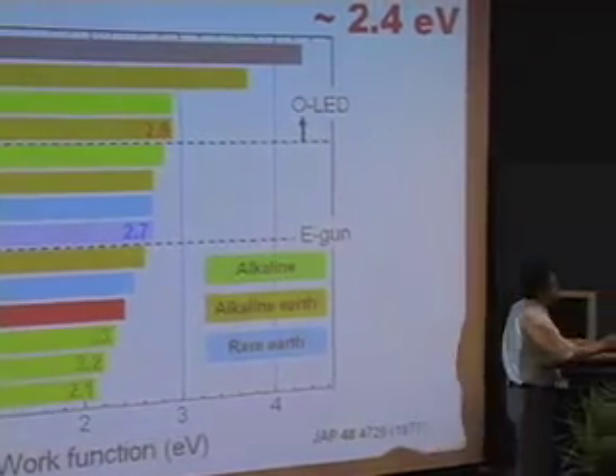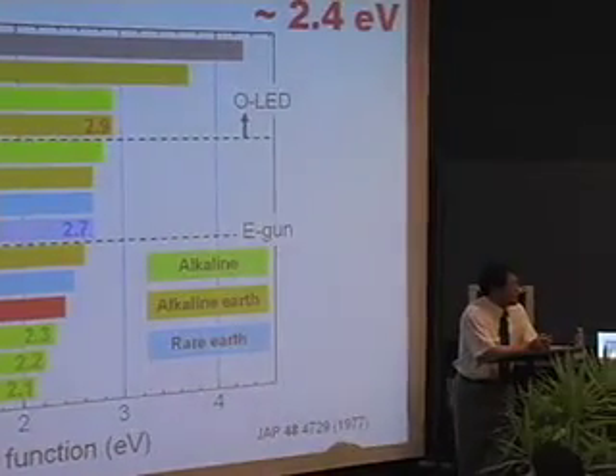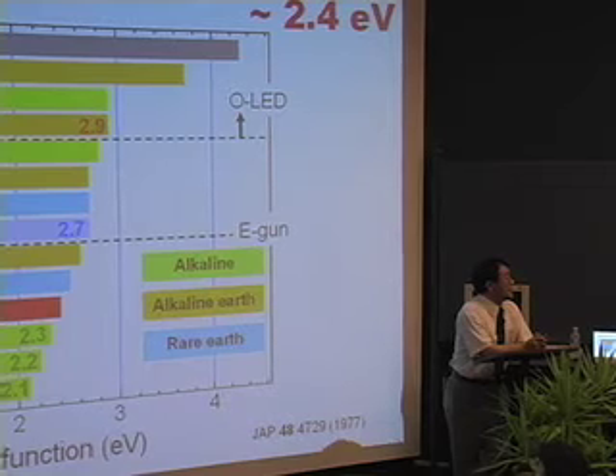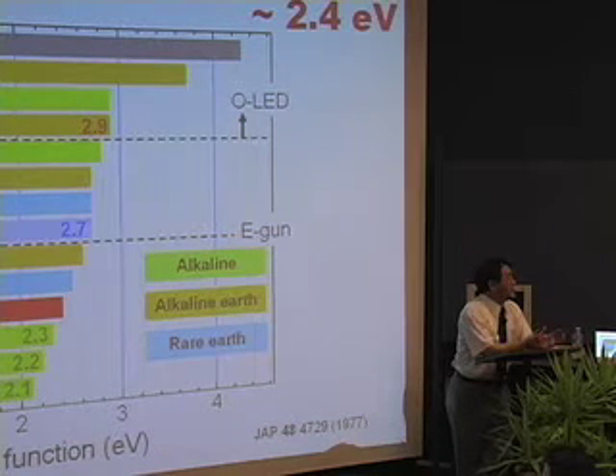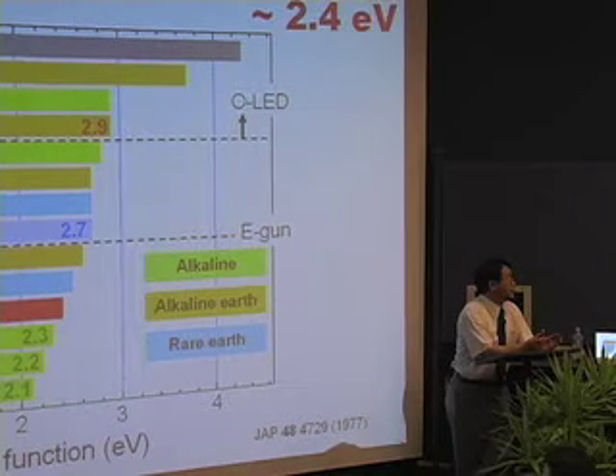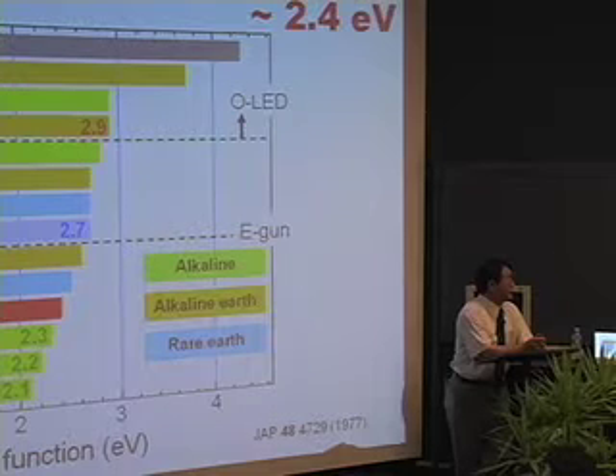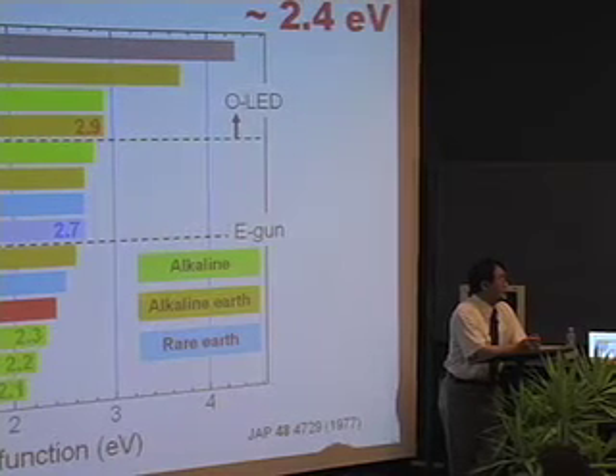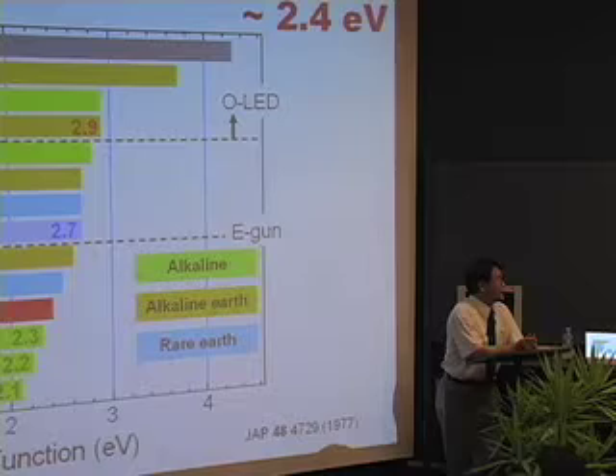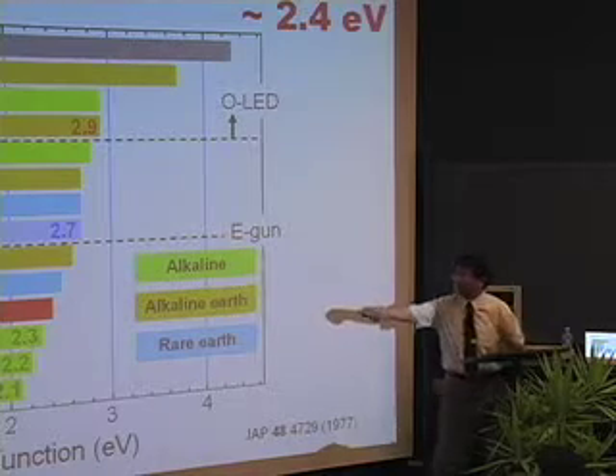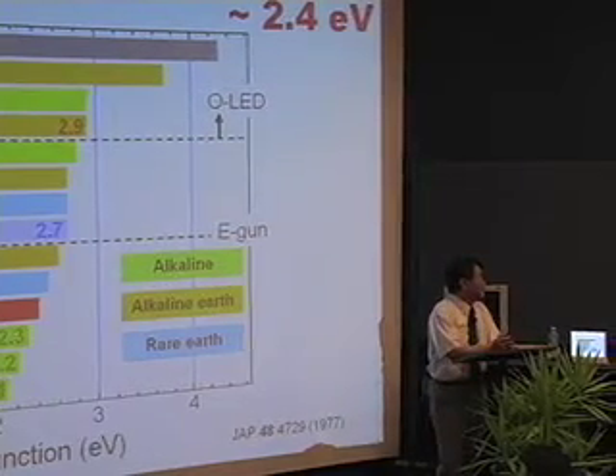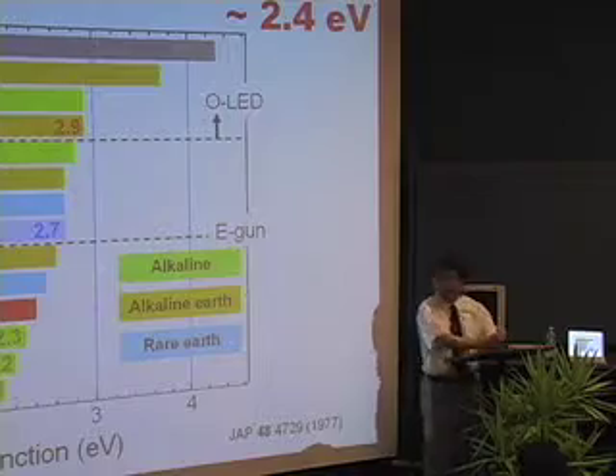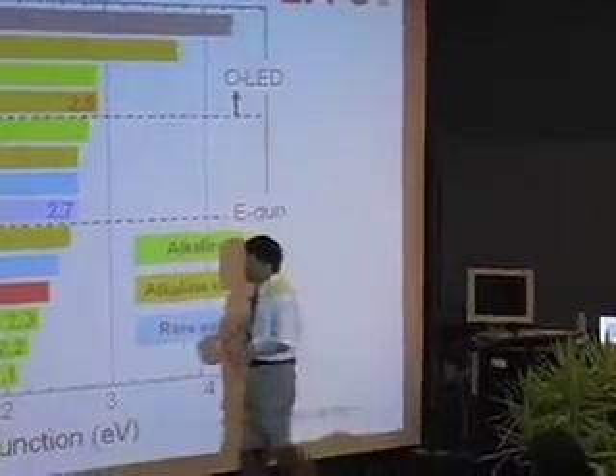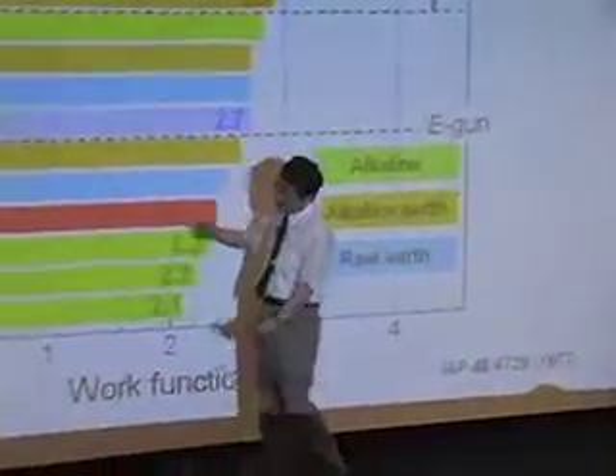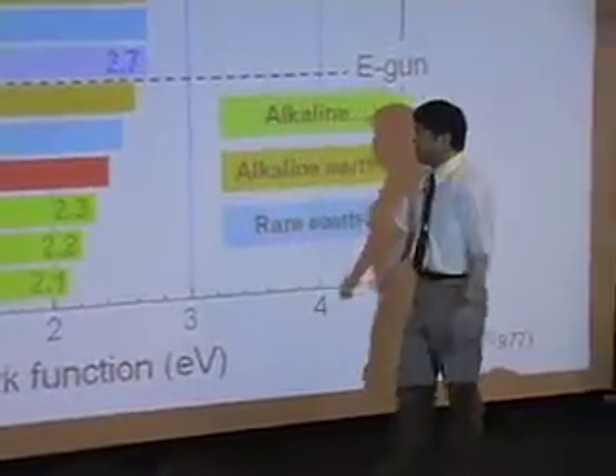Low work function metal is chemically very active. If you touch metal potassium by hand, what happens? It's chemically unstable, too reactive. But we can touch the C12A7 electride by hand — it's pretty chemically stable. And the melting temperature of this material is 1200 degrees C, very thermally stable.